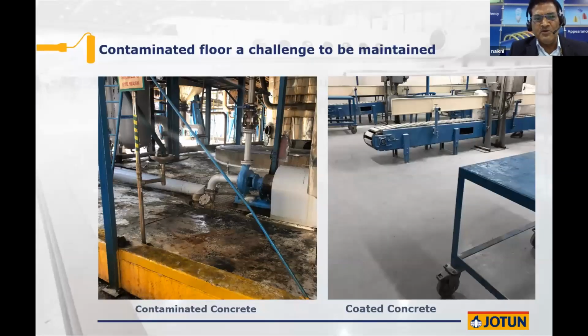These two images on your left and the right, you can see clearly from the left image, the level of contamination in a factory is so deep that even if you want to remedy this, it will take you a lot of effort, but you will never be 100%. And the picture on the right is also a factory. It's a redone floor, but you can see it's much better than the one on the left, but still you can never be 100%. So contaminated floors is always going to be a big challenge to remedy or to bring it back to top-notch 100%.